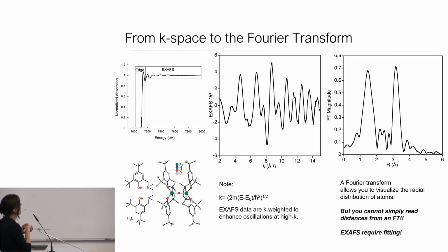But normally in a publication, what you'll see is something in K space, which is reciprocal angstrom space, that I arrive at by converting from energy space, and we'll go through exactly how you do that. And the EXAFS is typically K-cubed weighted. And then what we do is we take K space, transform it into R space in angstroms, and we get this sort of Fourier transform where these features indicate the radial distance relative to the photoabsorber at 0.